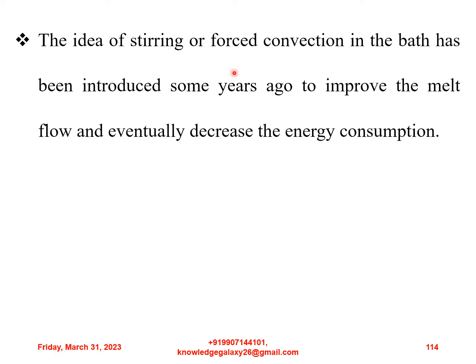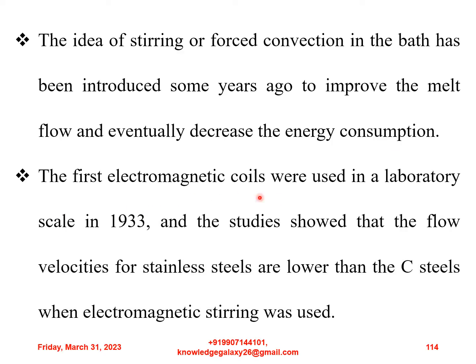The idea of stirring or forced convection in the bath has been introduced some years ago to improve the melt flow and eventually decrease the energy consumption. The first electromagnetic coils were used in a laboratory scale in 1933, and the studies showed that the flow velocities for stainless steel are lower than the carbon steels when electromagnetic stirring was used.